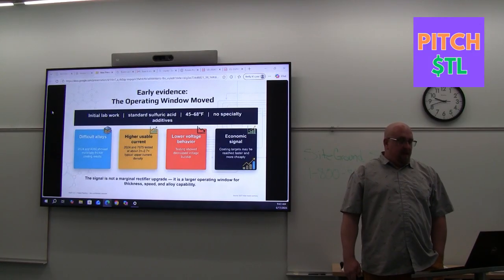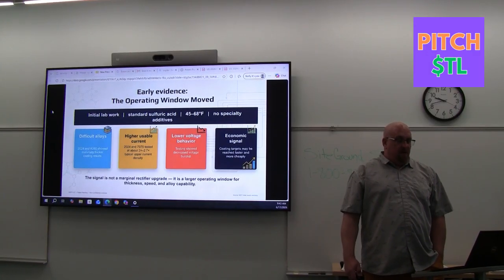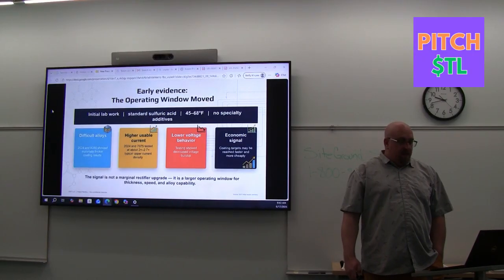In initial testing, using standard sulfuric acid, moderate temperature, and no specialty additives, we observed a meaningful movement in the process window. Difficult alloys such as 2024 and A380 resulted in coatings up to 4 times thicker. Standard alloys, including 6063 and 7075, were successfully run at up to triple the threshold of established safe maximum current density limits. Testing also showed decreased voltage buildup compared with standard rectification behavior, in some cases dropping energy input by up to 25 volts. This is a very significant decrease in energy consumption. Of course, these are initial results, not the end of validation, and not maximally optimized. However, these strong indicators of performance justify continued development, independent revalidation, and pilot testing.